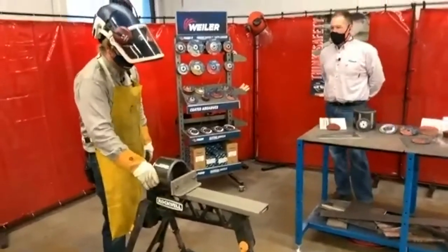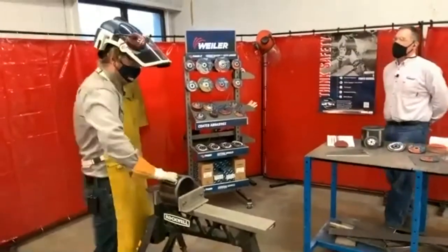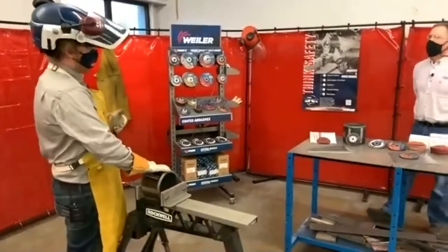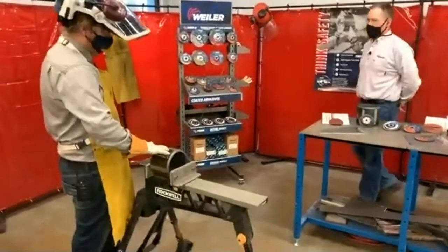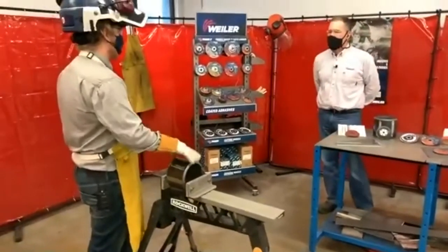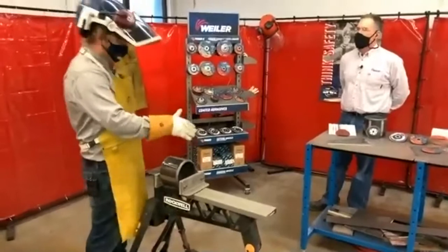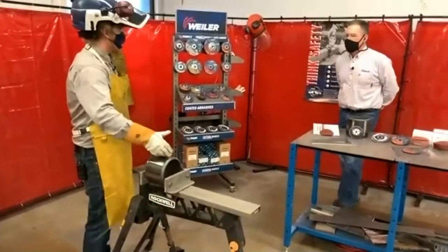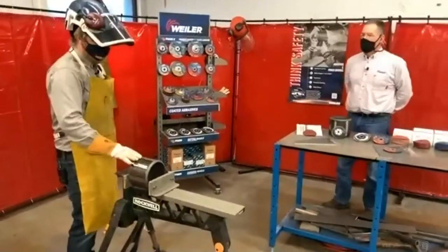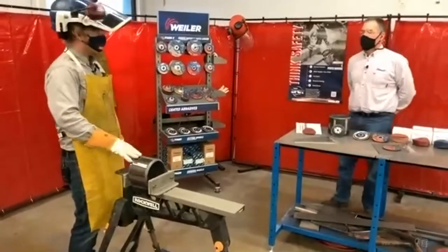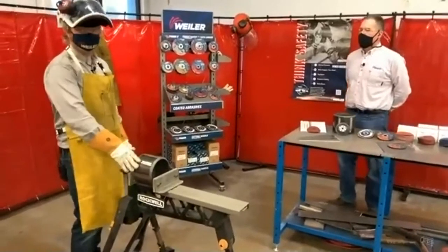The issue I had with the bonded abrasive is that I feel I have a deeper cut. So the issue with that is I could potentially cause harm to the parent material and maybe have to re-weld and refinish it. So keep that in mind too, as far as the contact patches and what abrasive you're using on a conformable surface.